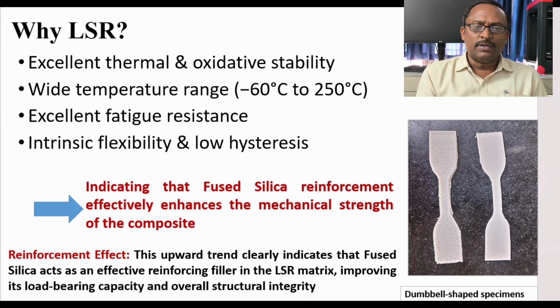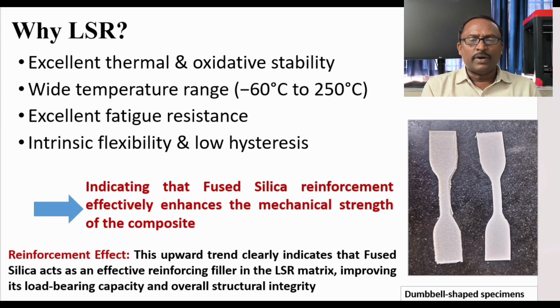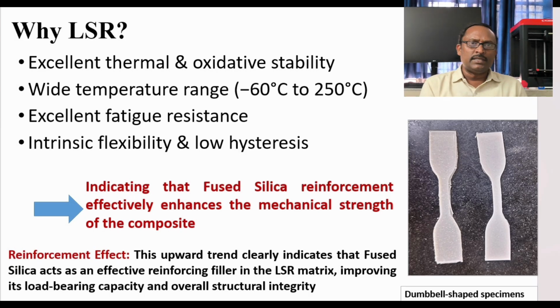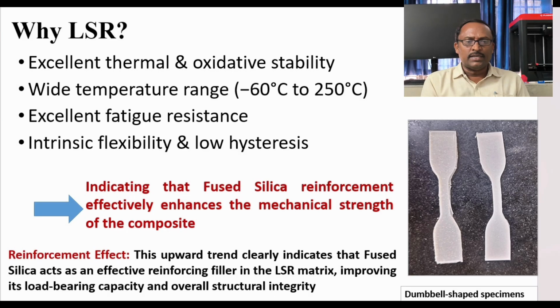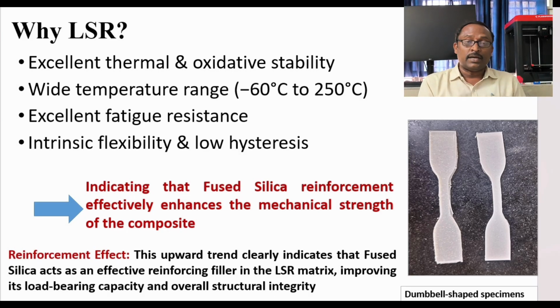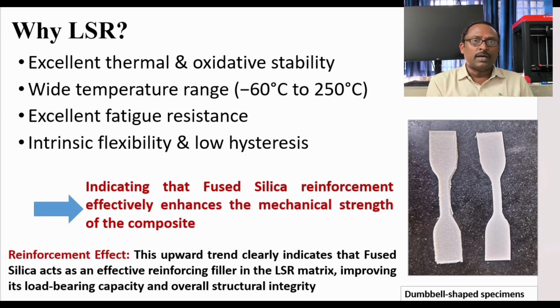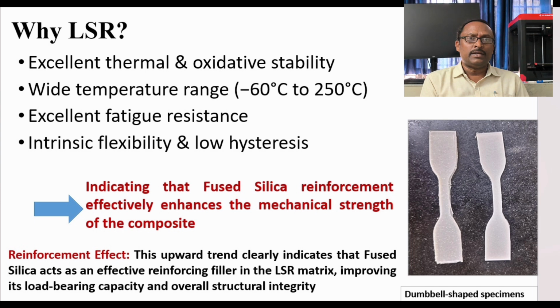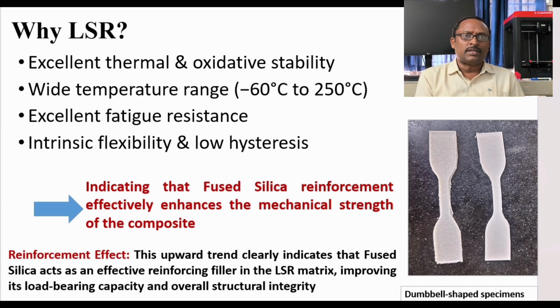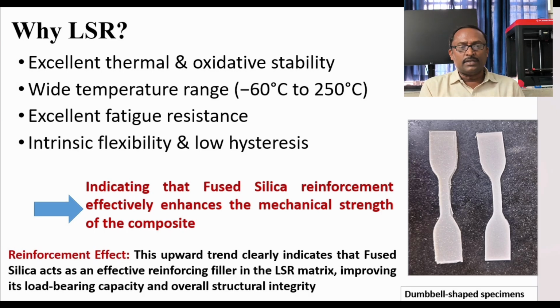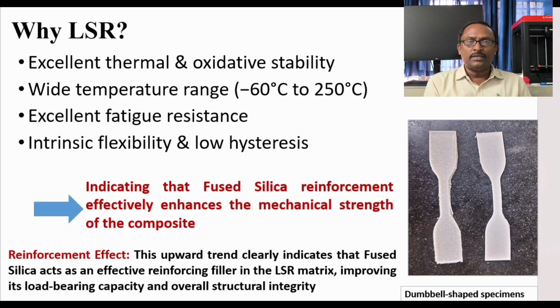Yes, excellent thermal and oxidation stability. Wide temperature range from minus 60 degrees centigrade to 250 degrees centigrade. Temperature resistance is required for the tire because it is moving with a high velocity. Certainly, fatigue and friction are generated between the road and tire. That resistance should be given by the material, along with excellent fatigue resistance, intrinsic flexibility, and low hysteresis. So you can see the diagram very clearly.